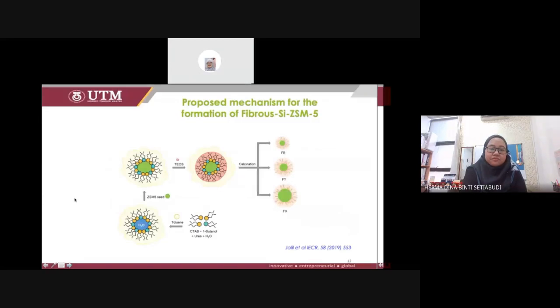Okay, back to the synthesis mechanism. We propose the mechanism of the fibrous silica, this is just an example, fibrous silica ZSM5. We propose the mechanism is like this. Because we are running out of time, I just show the proposed mechanism. So as I can summarize, we can replace the seed of the ZSM5 here with any other seeds, so we can produce fibrous silica with any materials.